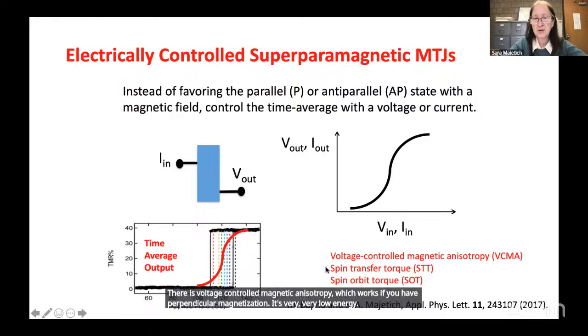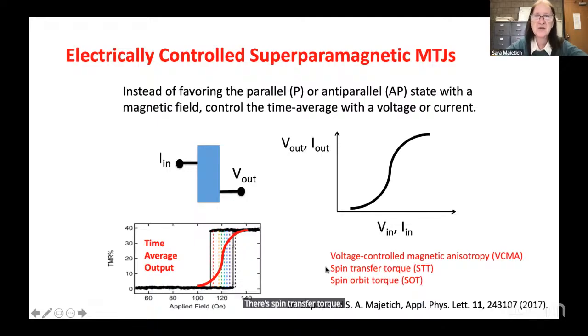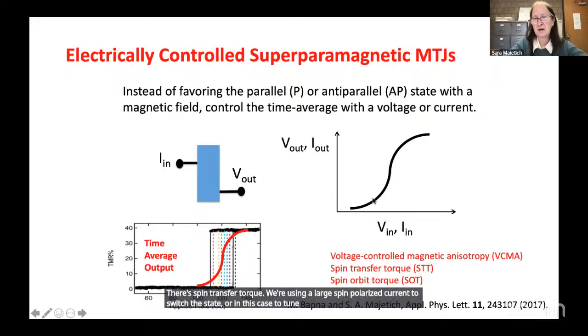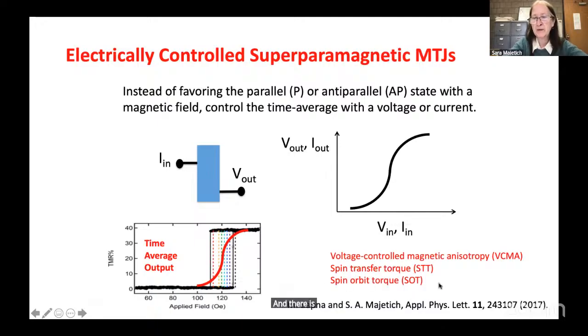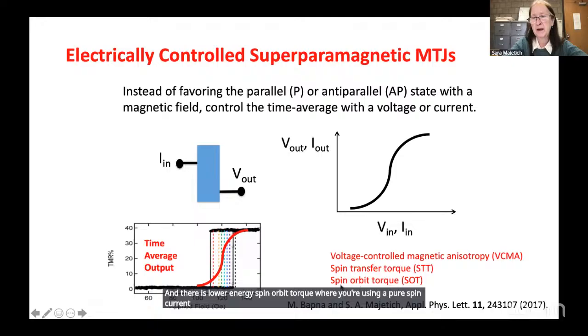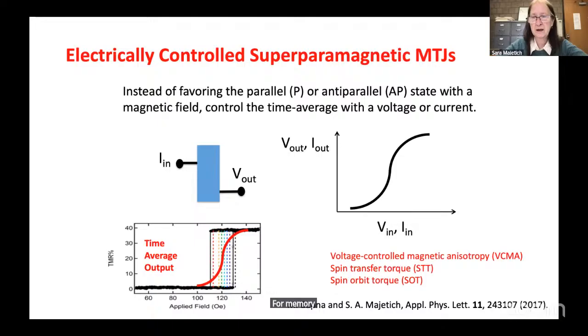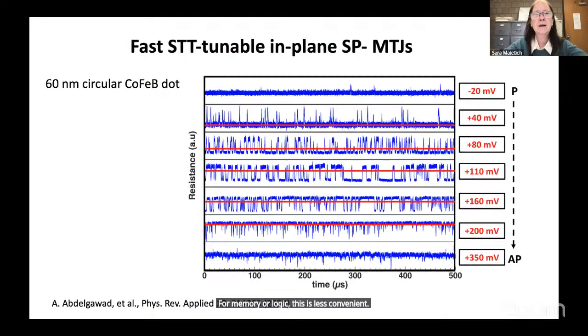There's spin transfer torque. We're using a large spin polarized current to switch the state, or in this case, to tune the position on the sigmoid curve. And there is lower energy spin orbit torque, where you're using a pure spin current generated by a real current through a heavy metal. The difficulty of the spin orbit torque is that it requires a three-terminal device. And if you're wanting to use, say, a crossbar array for memory or logic, this is less convenient.